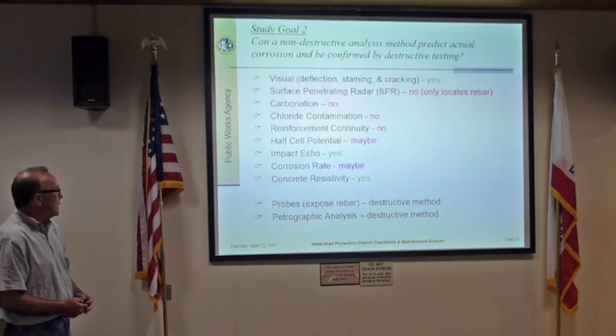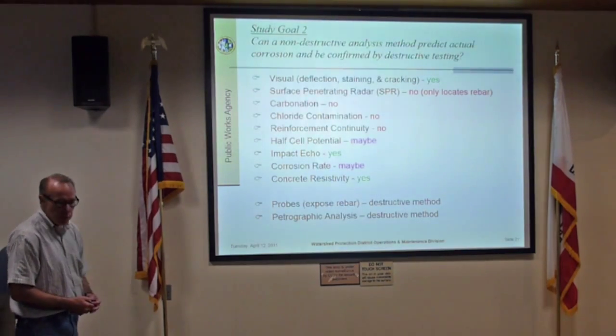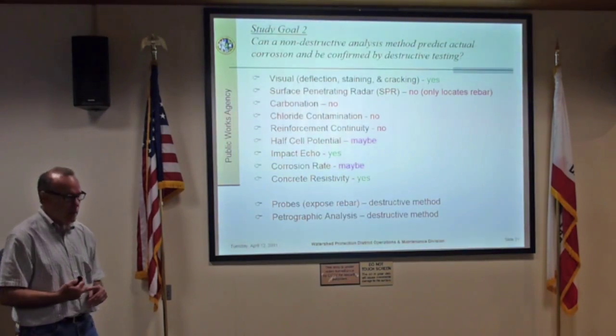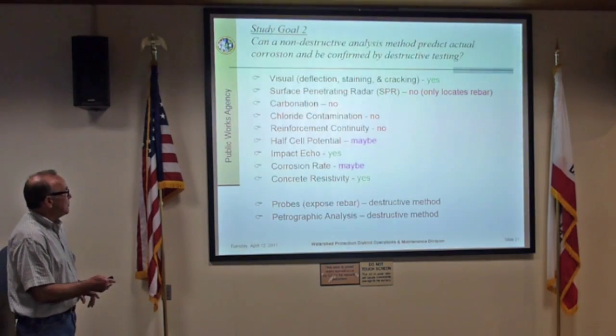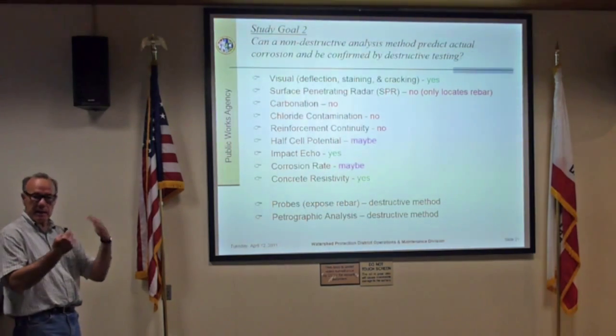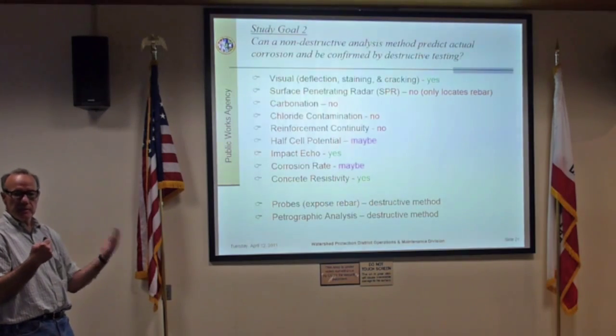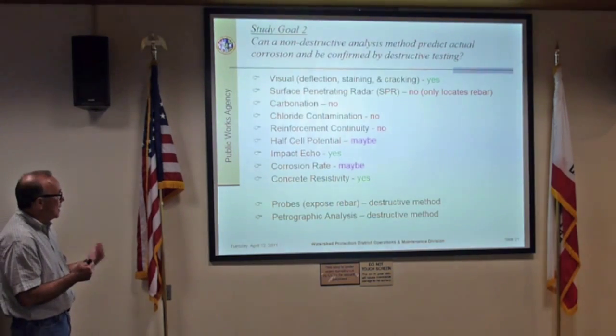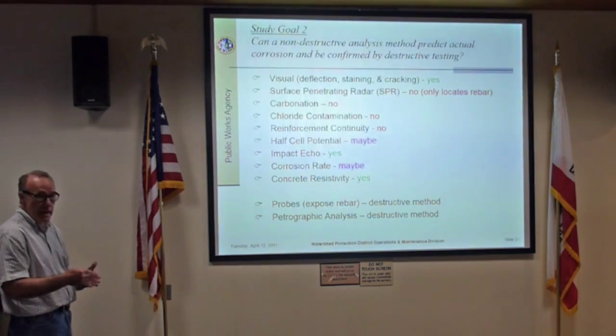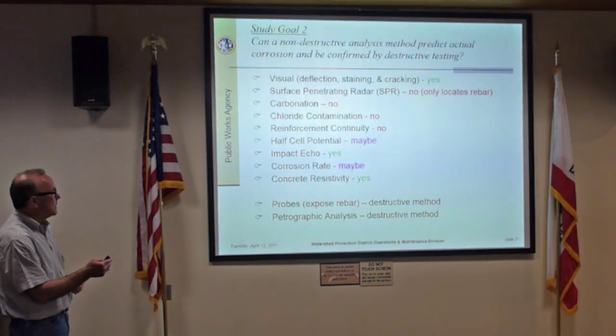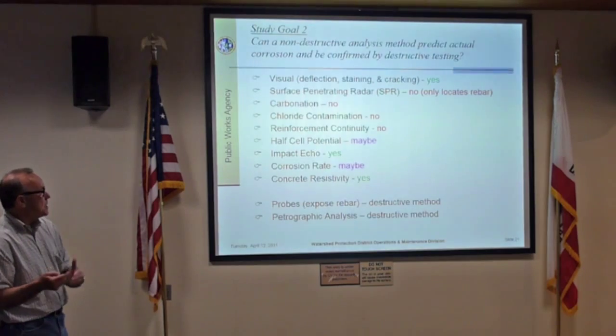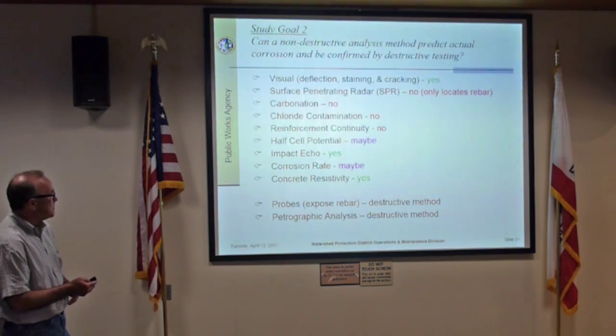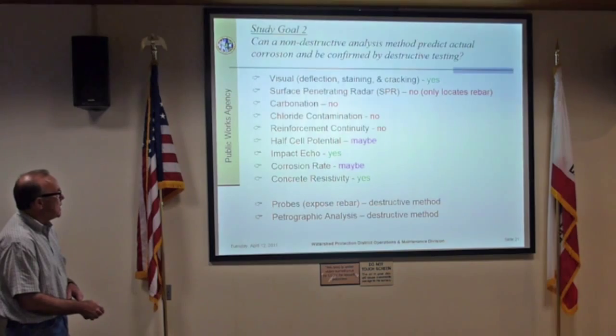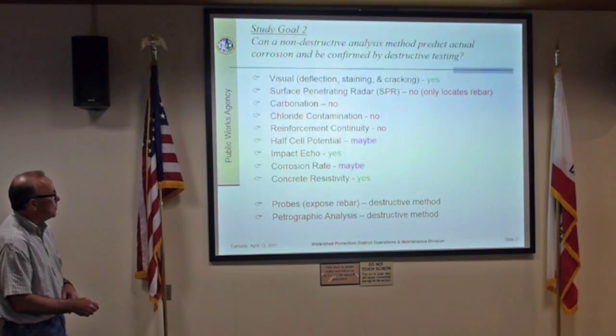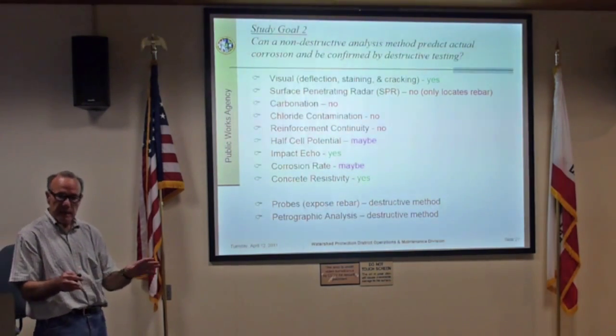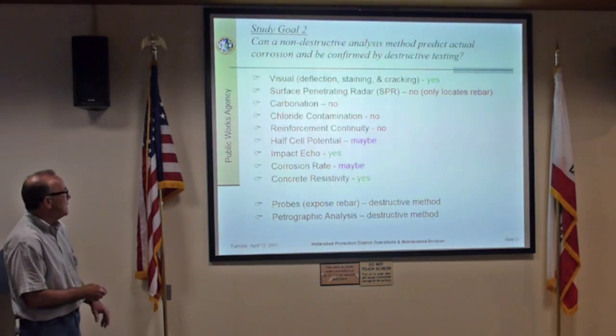So in summary, we look at study goal 2 from the aspect of what we can use from NDT. Visually, of course, when you get to cracking and movement, it's already getting too late. It's holding on by a thread at that point. But certainly we can use visual indications if you do that on a routine basis. It certainly is helpful from an agency point of view doing routine visual inspection. Surface penetrating radar is only good for locating the rebar, but then it gives us an avenue for going in and inspecting it.